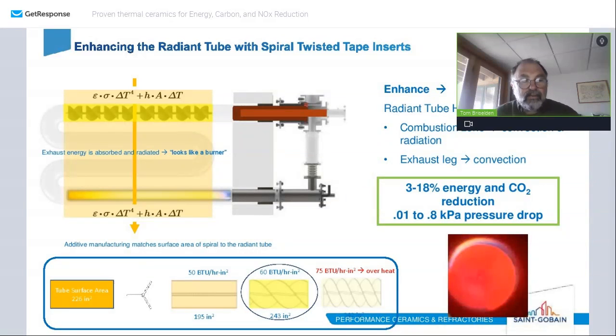Additive manufacturing, as compared to slip casting or injection molding, allows the twist rate to be easily modified and optimized for a given radiant tube. While increasing the twist rate further enhances the heat transfer, overheating may occur. However, this may be an advantage, for example, in a radiant tube made of ceramic. Typically, 3 to 18% energy and CO2 reductions occur with minimal pressure drop, usually on the order of about 0.01 to probably a maximum of 0.8 kPa.